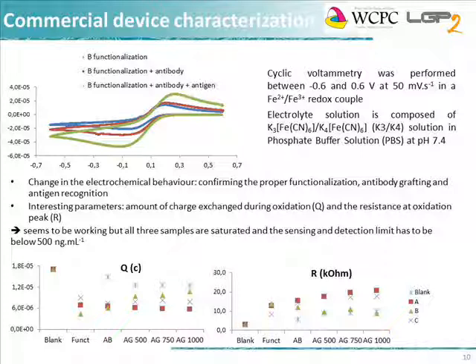It serves as a first confirmation of the success of the different steps: the functionalization, the antibody grafting, and the antigen response. From these CV curves, quantitative information can also be extracted. 2 parameters were particularly looked at: the amount of charge exchanged during oxidation, Q, and the resistance at oxidation peak, R. The variations of those parameters are also interesting for concluding on the experiments.